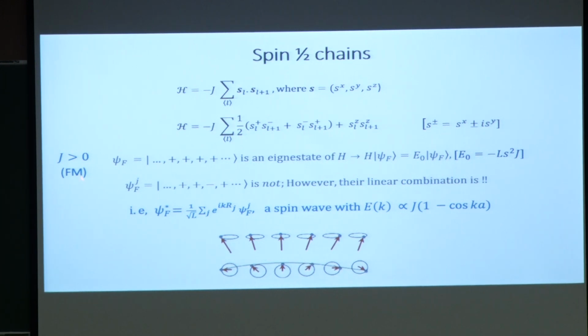Okay, and then you can show that if you construct a state where all the spins are pointing in the same direction, and you act with this Hamiltonian on it, you will see that this state that you have prepared actually is an eigenstate of your Hamiltonian. So that means this is the true ground state. So for a spin 1/2, all up is very much allowed, and this is the energy.